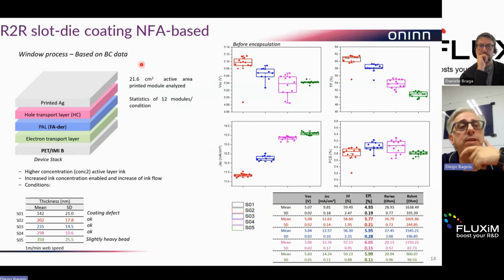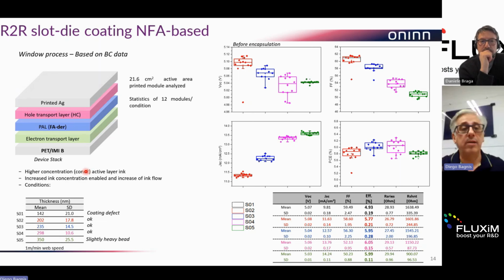On the other side, when we take these results and move to the roll-to-roll slot die coating, we are still speaking about roll-to-roll in the R&D. We have several pieces of equipment, but here it is still R&D. So with the non-fullerene acceptor derivatives, to change the thickness, one of the parameters we tend to work on is to increase the concentration, because the formulation created on the blade coater is not the same used in the roll-to-roll, for several reasons. One of them is connected to the fluid dynamics involved.